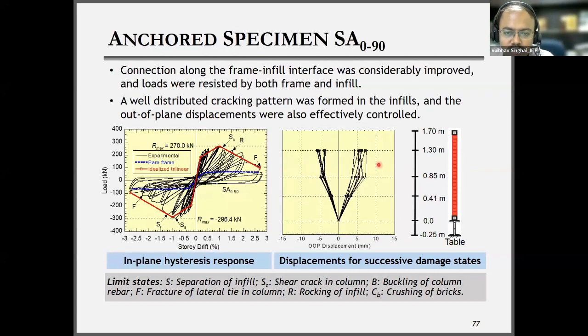Now these are the responses for the anchored ones, where we used anchors to attach the fabric to the surface of the masonry or to the surface of the frame. Definitely, as expected, this has performed better, especially if you see the out-of-plane displacements. Even with the extensive damage, they were always less than 10 mm, close to 5 mm.